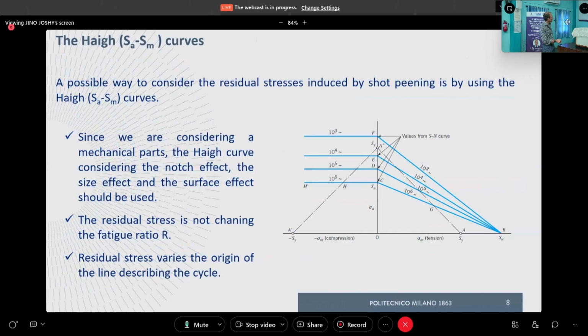It is also possible to see that if we are considering tensile residual stresses, the effect is the opposite. The amplitude will be much less than the condition without residual stresses. Okay, it's clear this concept. So what we can do with the traditional Haigh diagram is this: the residual stress moves the origin of the cycle and increases the amplitude we can apply before reaching the limit point.